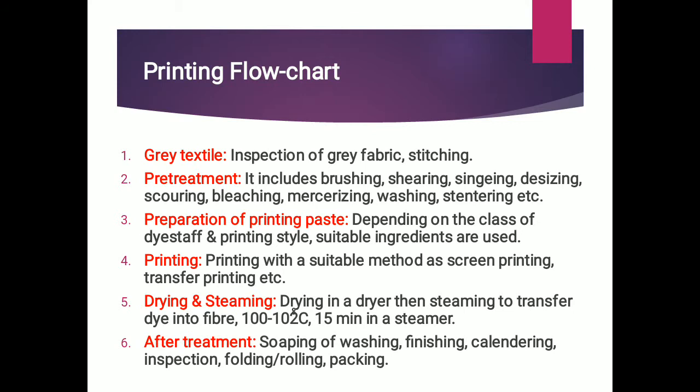Then drying and steaming is performed at 102 degrees centigrade temperature in a steamer. After treatment may be of different types — it depends on the process, on the dye, and on the final requirement.